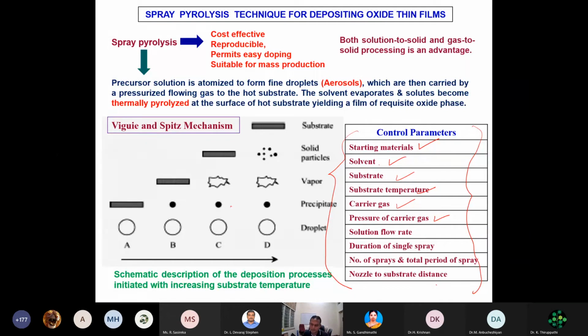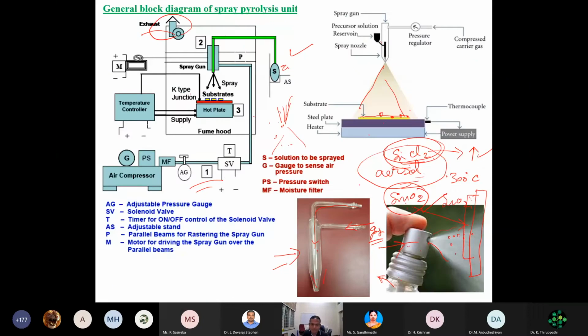And then when I spray this solution along with the compressed gas here, you will see that this solution along with the compressed gas will cool this substrate. Say for example, when I keep 400 degrees centigrade, when I spray once, the temperature will come to almost 325 degrees centigrade. So what I have to do is, I have to have an idea about the distance and the pressure and this cooling temperature and all. Because I have to spray this aerosol so that it should reach the temperature where its decomposition point should be satisfied.